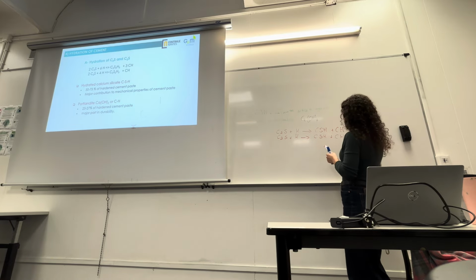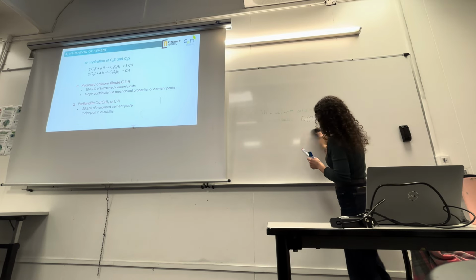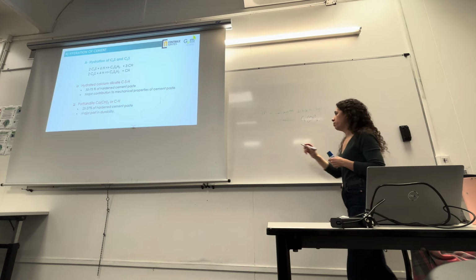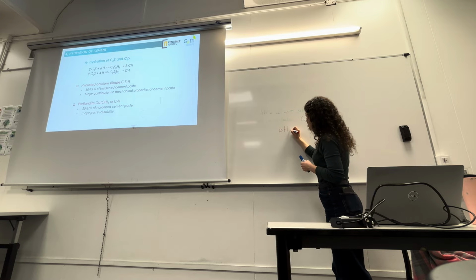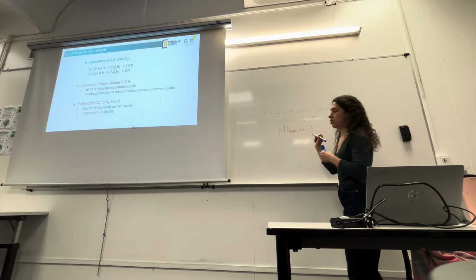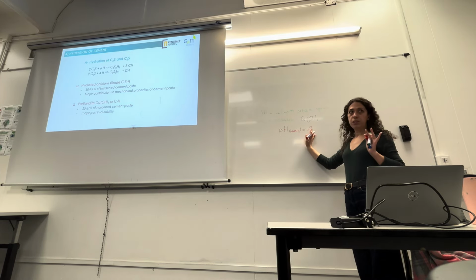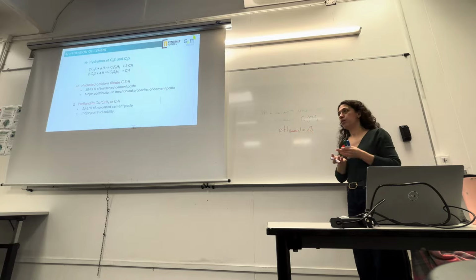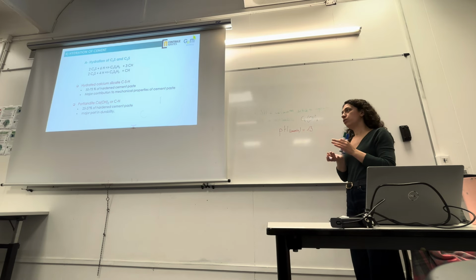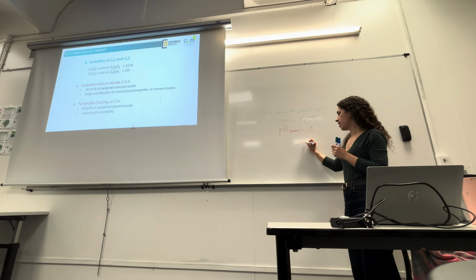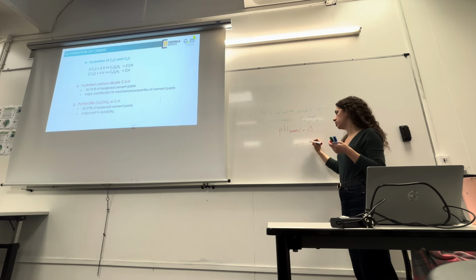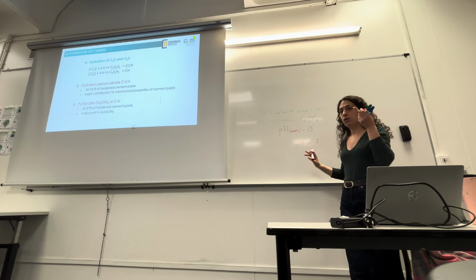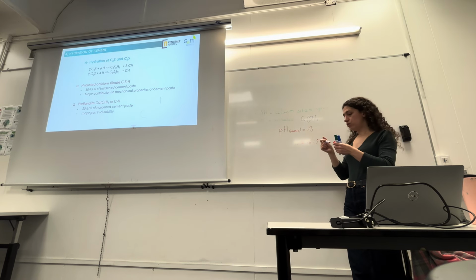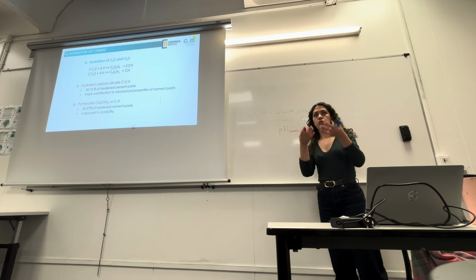How? Because the pH in concrete pore solution is around 13. So it's a very basic pH. And you know that water in the environment is mostly around 7, and even sometimes more acidic, 6, or maybe 5. So it is very acidic to concrete, very aggressive to concrete. So water destroys concrete, water destroys the cement paste.